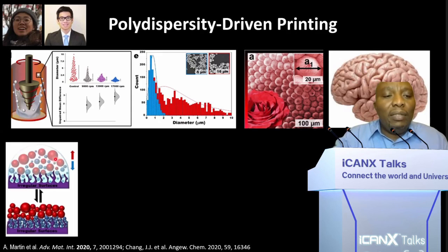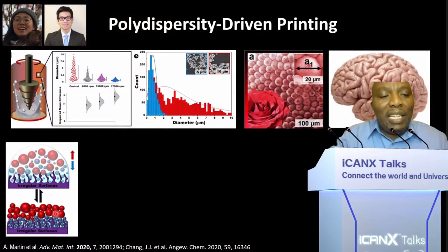The science behind it is that if you put a slurry of particles on a textured surface, through self-filtration you get all the small particles to occupy the deepest crevices, and the big ones will stay on top. When you sinter these particles, you get very nice conformal electrodes forming on top of whatever texture you have. And there are statistical tools that allow us to predict very well what kind of distribution we're going to get. This work just came out in Advanced Materials Interfaces.